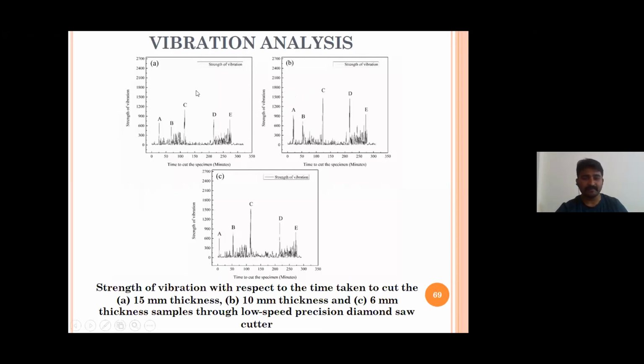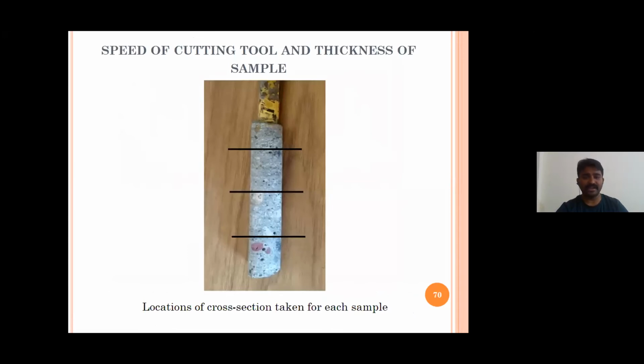See here, for 15 mm thick samples, this is the vibration chart. For 10 mm, this is the vibration chart, and for 6 mm, this is the vibration. From this, what is the inference that we are getting? As the thickness reduces, the vibration increases at the steel concrete interface, which will affect the interface properties. And where did I cut? I took the samples at three locations. One is here, one is here, and one is here. So at this, there are three samples: 15 mm, 10 mm, and 6 mm. Likewise, we have taken the cross sections.